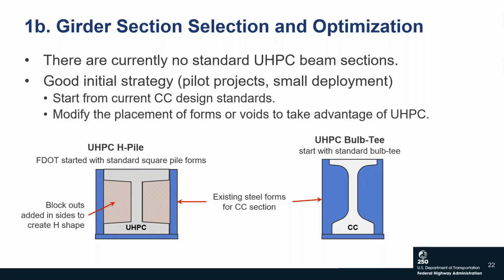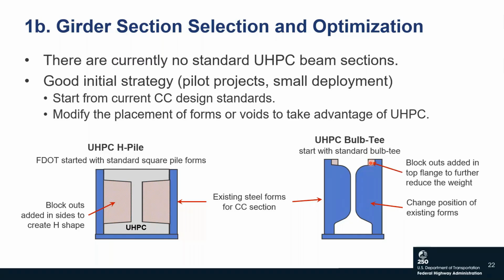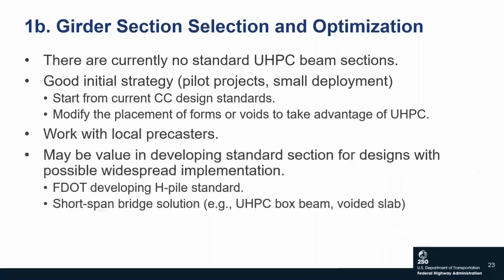Another example would be using bulb T forms that a precaster already has, looking to see if we can slide those forms in to decrease that web width. We can add some blockouts in the top to further decrease the weight of the section, taking advantage of the higher compressive strength of UHPC. Maybe modify the bottom soffit if we need to, and then cast the UHPC in that modified form. So again, you could use any formwork that you have at your local precasters and work with them to see how you can modify that formwork easily to be able to optimize your UHPC sections.